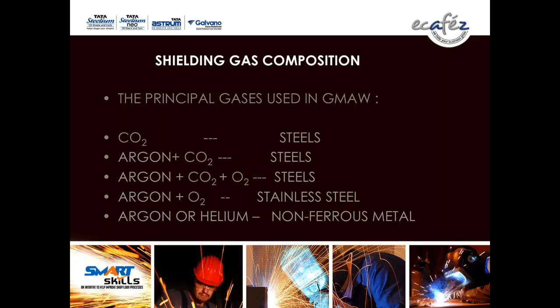Argon, CO2 and O2 mixtures are also available: 90% argon, 8% CO2, 2% O2. It can be used for steel also, for getting a good quality product. Argon plus O2, 98% and 2% or 99% and 1%, can be used for stainless steel in the MIG process. Argon, helium or an argon-helium mixture should be used for non-ferrous material in the MIG process.